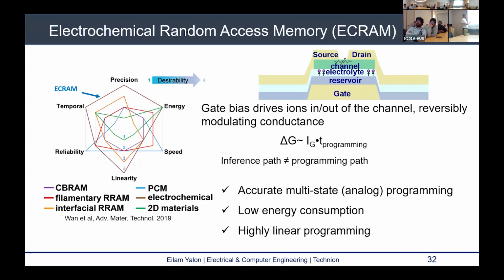One of the leading candidates for this type of application is electrochemical RAM, or ECRAM, which is essentially a three-terminal structure like a transistor. So we have two contacts, source and drain contacts, to a channel, and instead of the dielectric gate, we have an electrolyte and a reservoir. The concept is that we have a reservoir of mobile ions, for example lithium ions, and an electrolyte or some medium where these ions are mobile. And then with pulses from the gate, we can electrochemically drive ions into the channel and out of the channel.